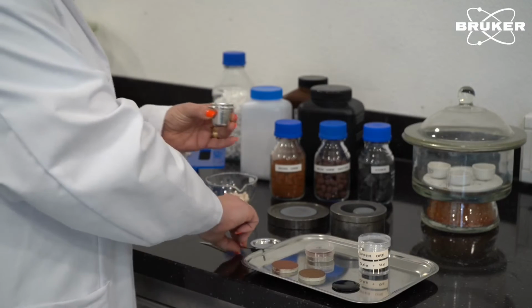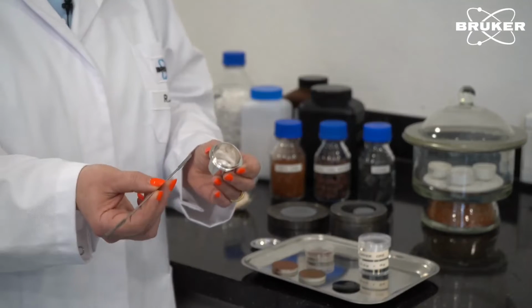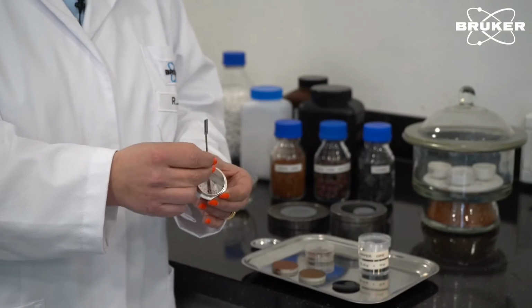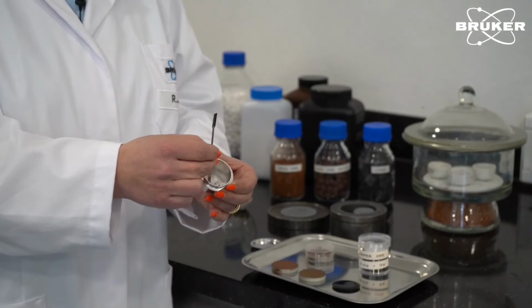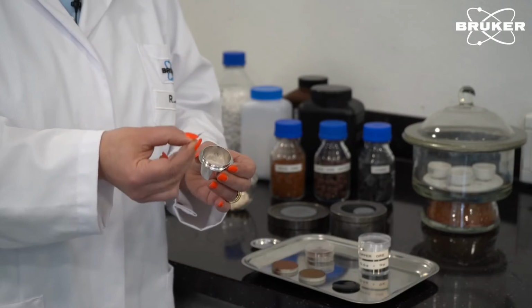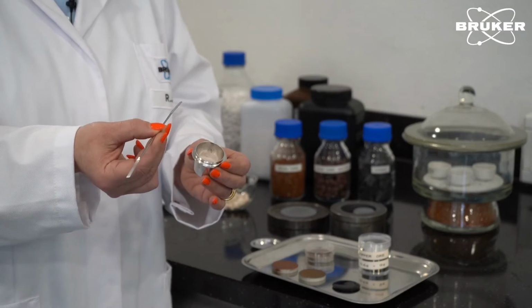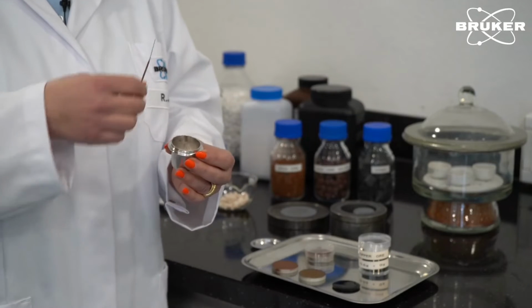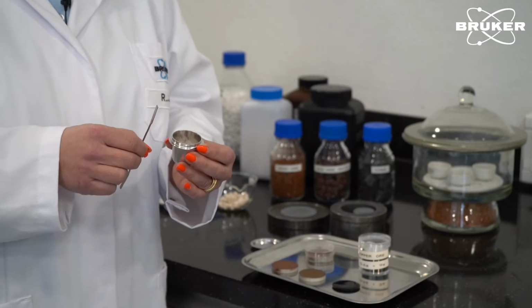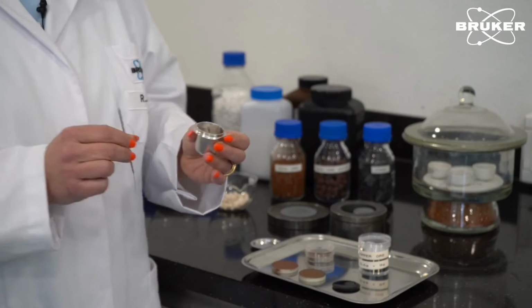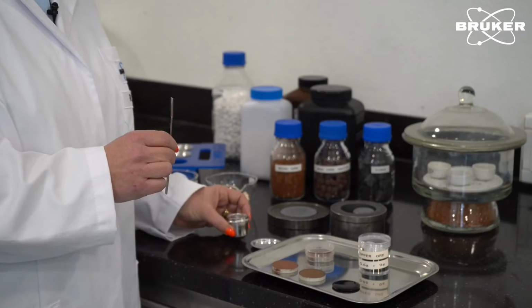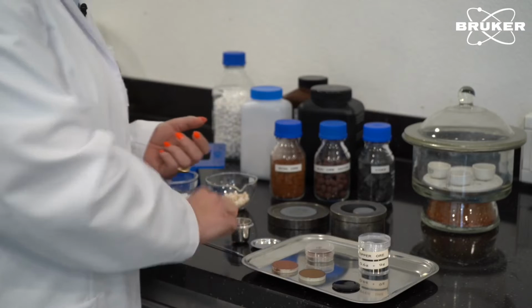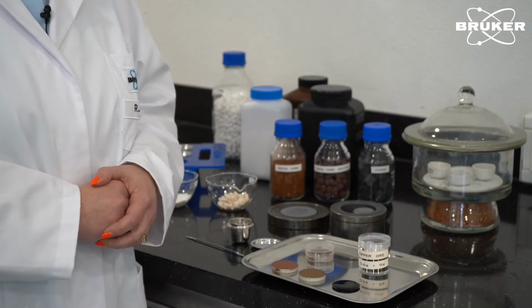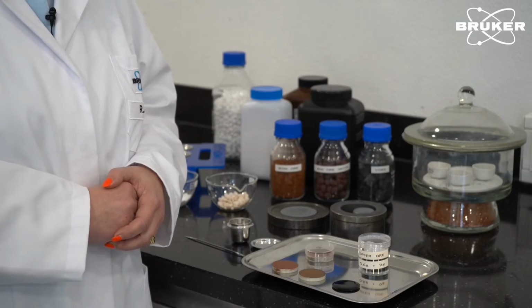In this case, I use a little spatula to mix the sample. I always try to avoid touching the platinum crucible inside with a spatula, so you can also use, for example, a glass one or a little spatula. After the sample is mixed, you can just put it into your fusion device and then the fusion process starts.